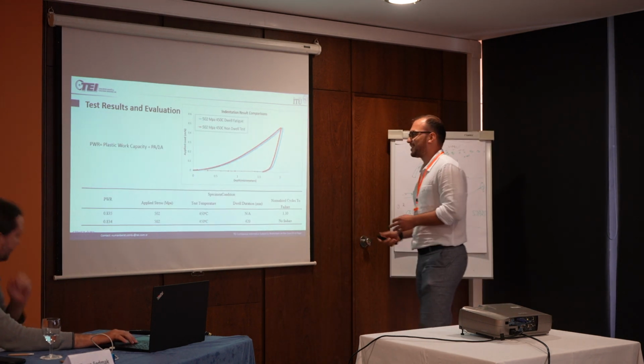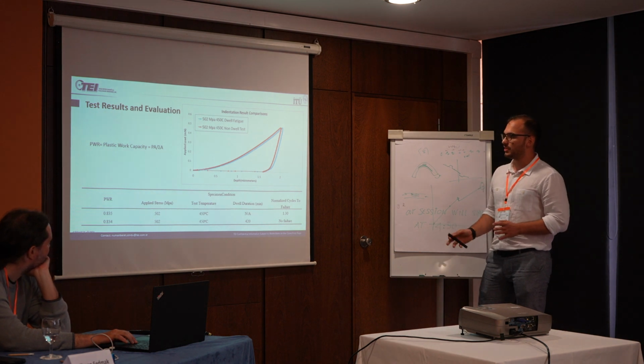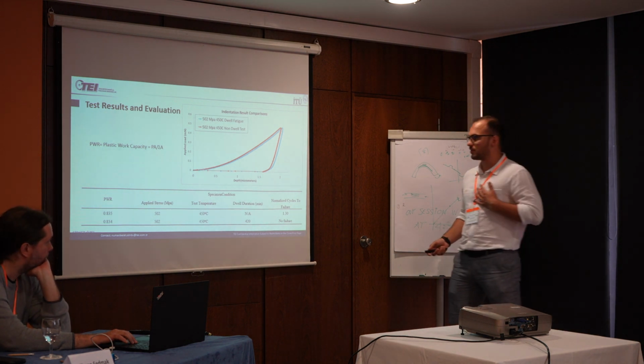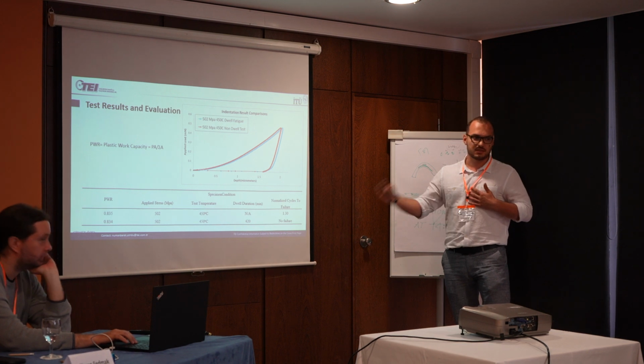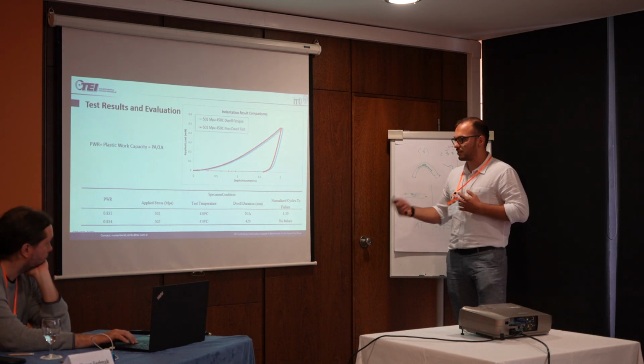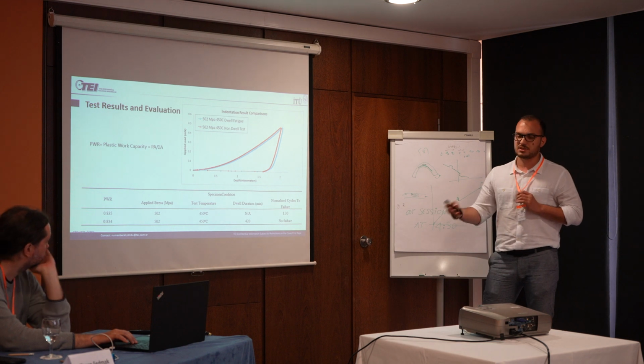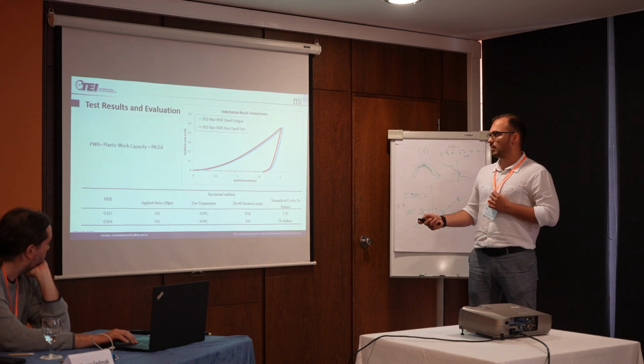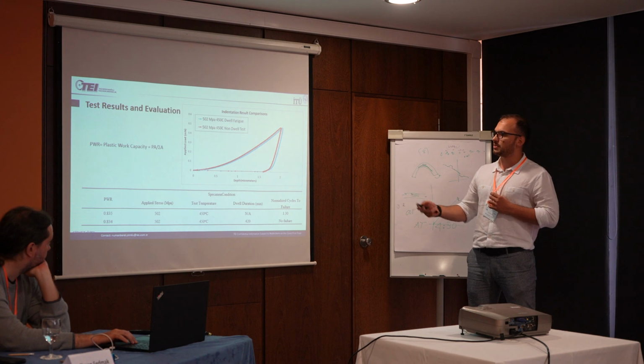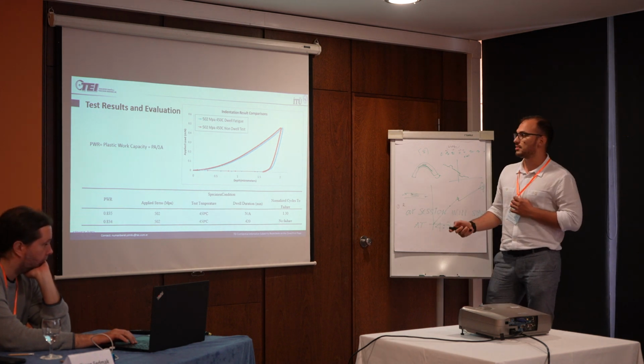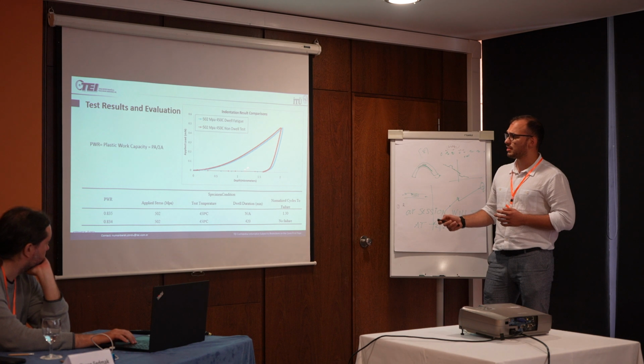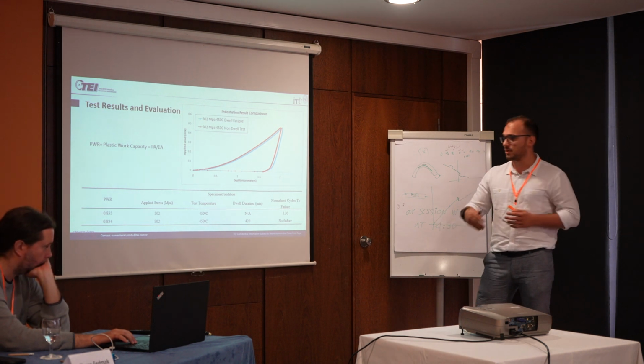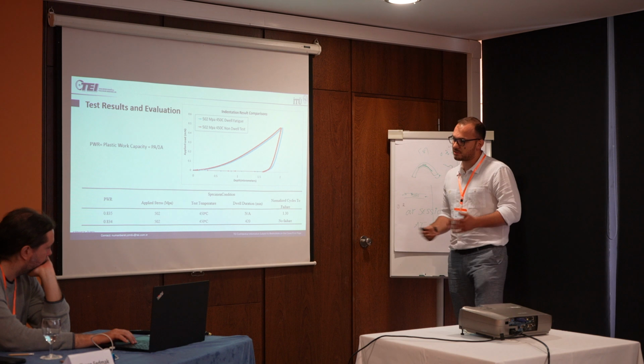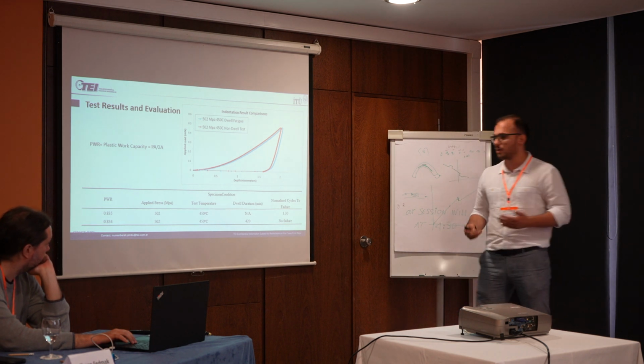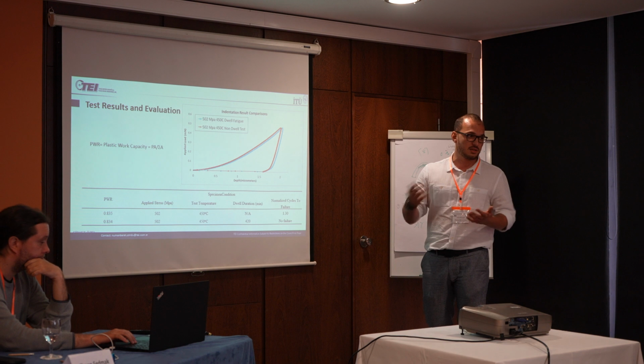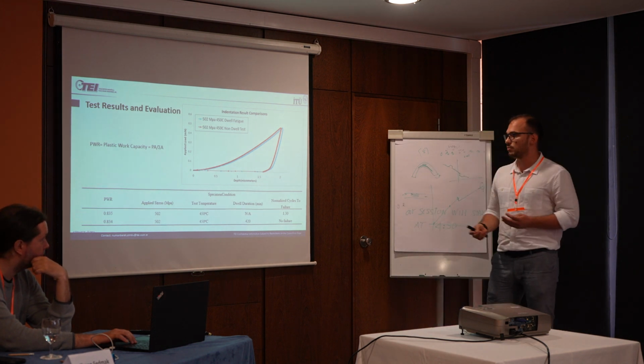Okay. So we applied the nanoindentation testing in order to see the plastic work capability of the dwell applied and non-dwell applied tests. Here, interestingly, we see that there is no significant change in plastic work capacity. By the way, we calculated plastic work capacity by simply calculating the area under the nanoindentation curves, and we saw that there is a similarity between them. So actually, it created another uncertainty. We can move on.